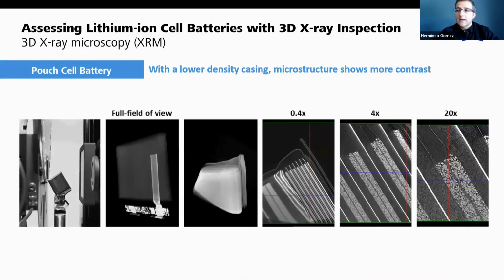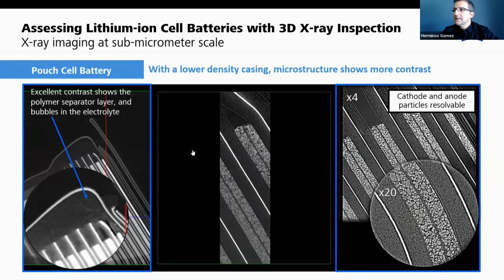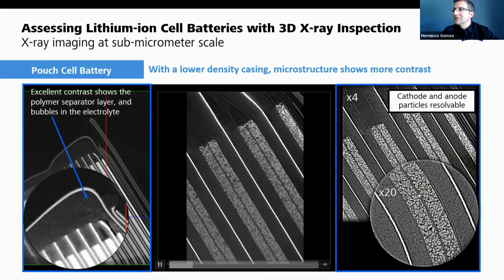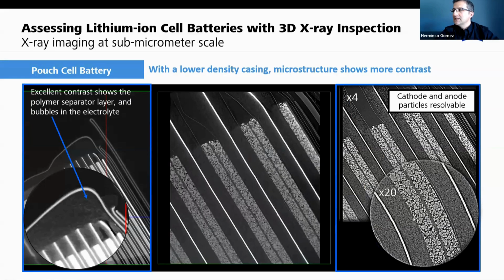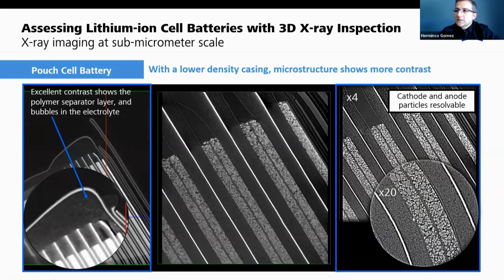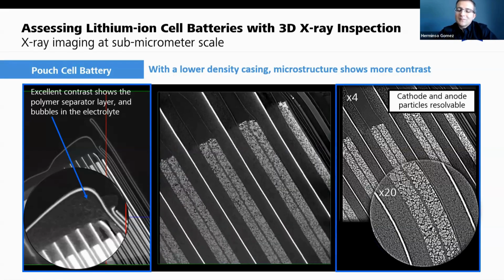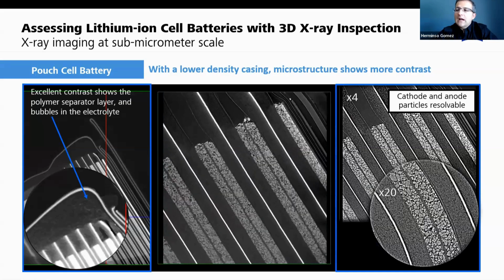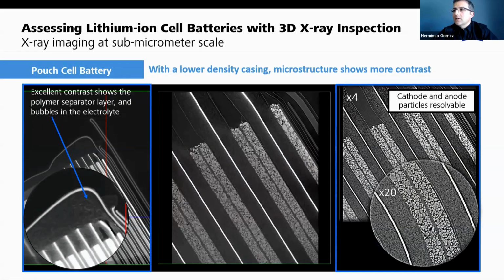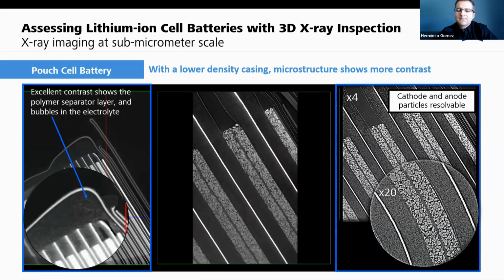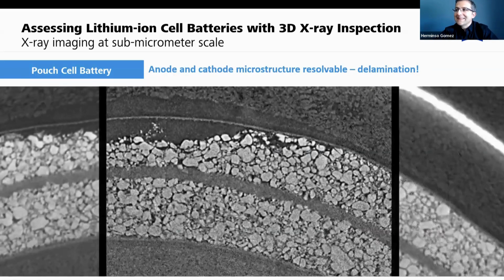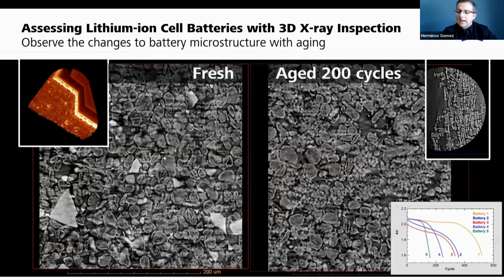And this is the workflow. Again, you generally take a full field of view scan of the full battery, and then you zoom in to see inside of the battery. Not only do you see the different electrodes, but you see the particle level, something that sometimes, when you use high energy CT or computed tomography systems, is very hard to see. So this is the main advantage that you will see with the X-ray microscopes in this case. And you can see some of the delamination.